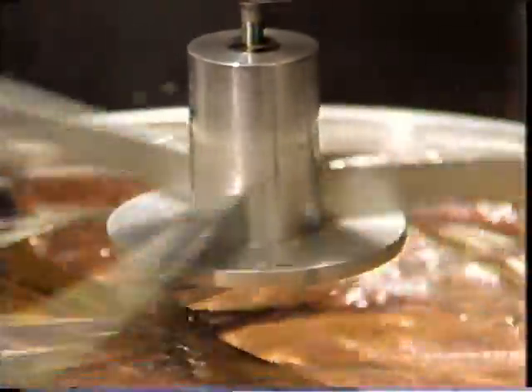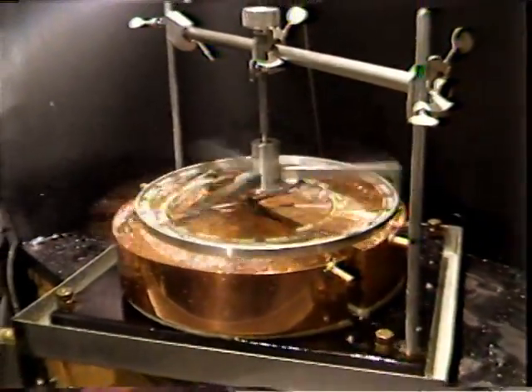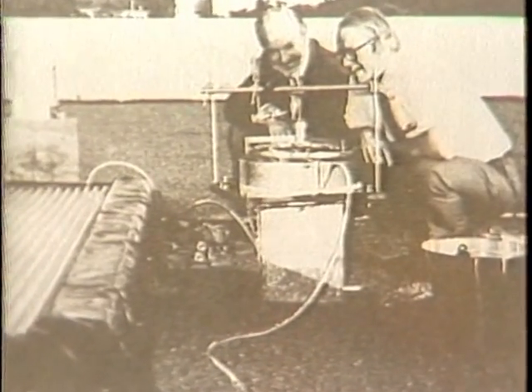This simple crankshaft wheel first began spinning one morning in November 1973 at the Lawrence Berkeley Laboratory, marking the first time that heat had been converted directly into mechanical energy. Ridgeway Banks rigged up a solar heater on the laboratory roof to keep the water warm enough to drive the engine and let it run to see if there would be any sign of fatigue in the nitinol wires. After 23 million revolutions, he found that the wheel was running stronger. No one is quite sure why this is happening. Professor McMillan reported the nitinol phenomenon in 1974 at a special meeting of Nobel Prize winning scientists in Germany.